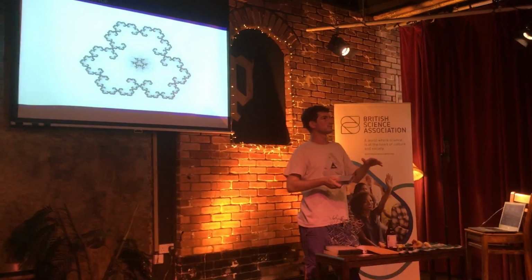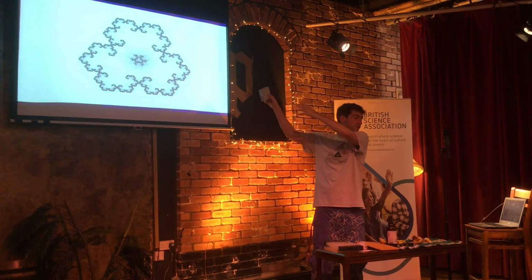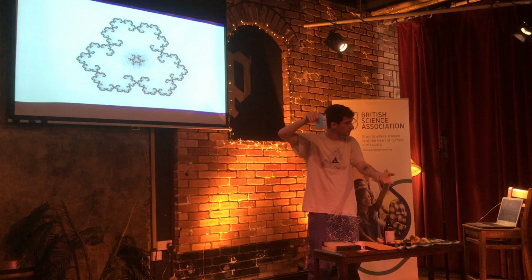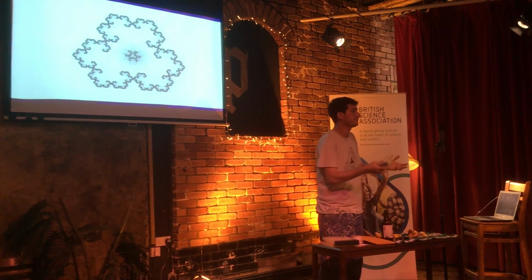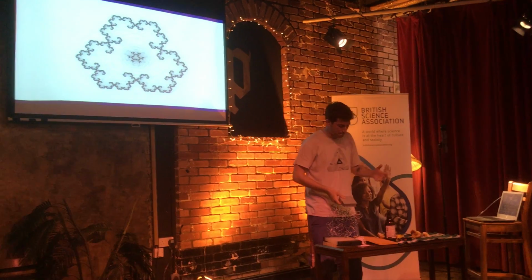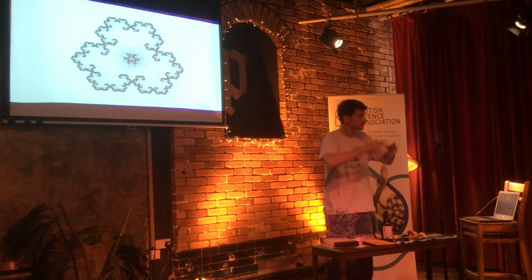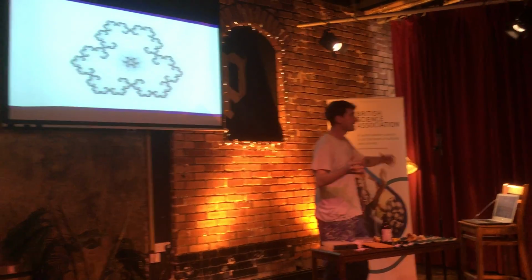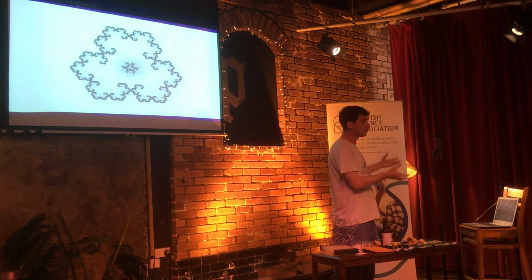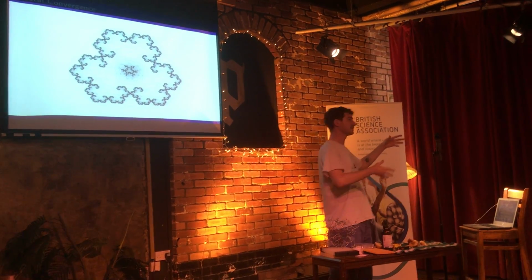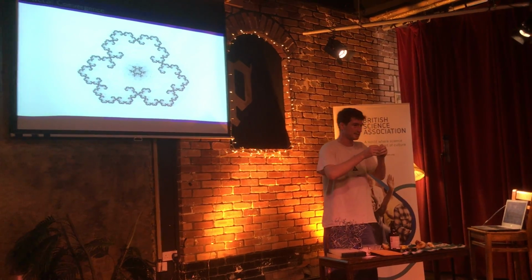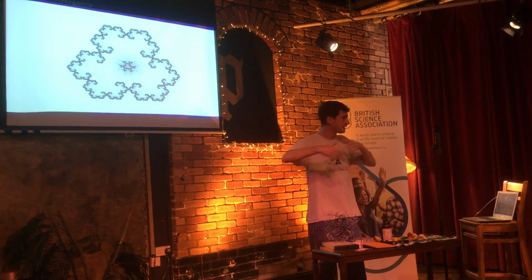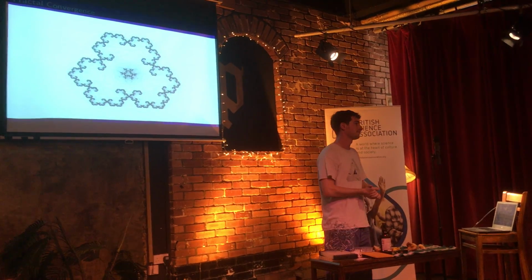So, in terms of when we have the crack that can open, honeycomb won't do that because it's easier for the cell wall to fail. But if we set the cohesion to be strong enough, then it acts in exactly the same way as honeycomb. So a honeycomb is something that we can effectively model with this. Right. We just need the right understanding of the material parameters for the cell wall, and then we put it into the model and it will work.